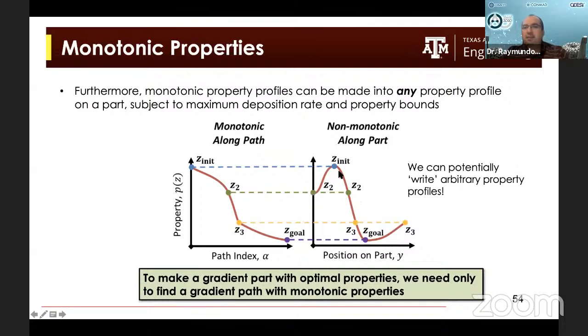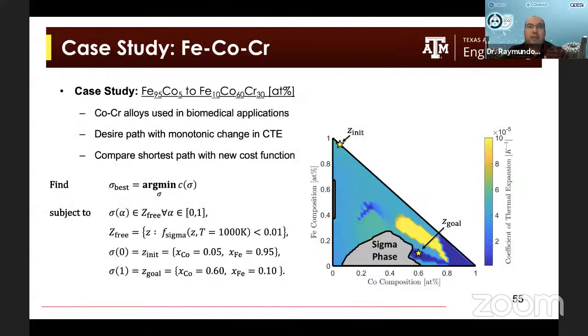So I can write a thermal expansion coefficient that changes sinusoidally, or that changes with a square pattern, or whatever, as long as the limits in the property are bounded by the path. And this transformation can be done. So I can transform this path to this path by just changing the deposition rate, changing how much I deposit of different powders. Okay. So what we did was we looked at the iron, cobalt, chromium system.